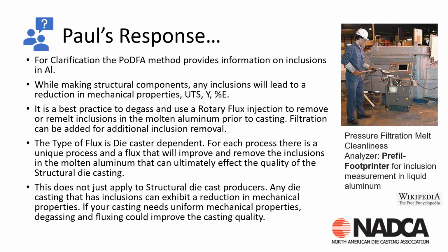For die casters, any inclusions in the castings, especially for structural castings, are going to lead to reduction of mechanical properties: tensile, yield, elongation. So if we have inclusions, we're going to see a reduction of mechanicals. The best practice that's available today is to degas and to flux the material. You can either use rotary injection flux, which is what I would recommend, or you can cast and work the flux in. But in either case, you're using flux to either remelt those inclusions back into the molten metal or to remove them and have them float to the surface so they can be skimmed off.